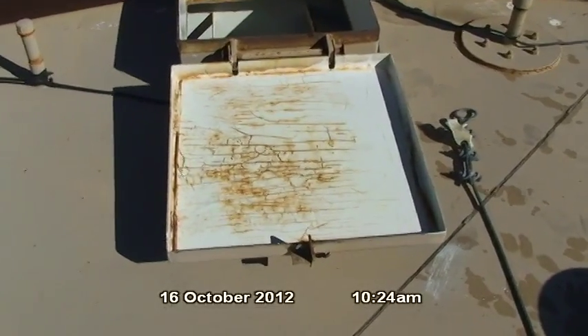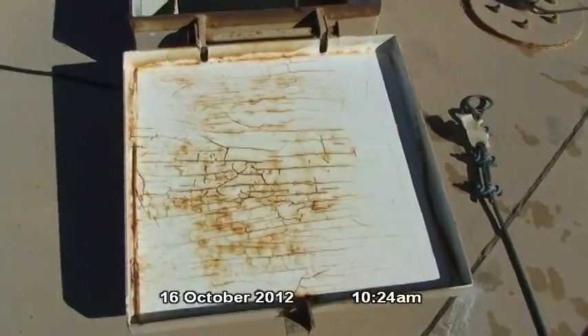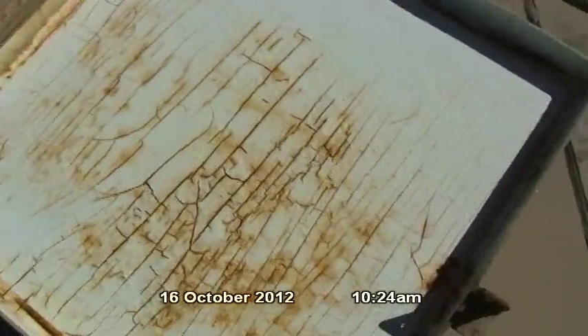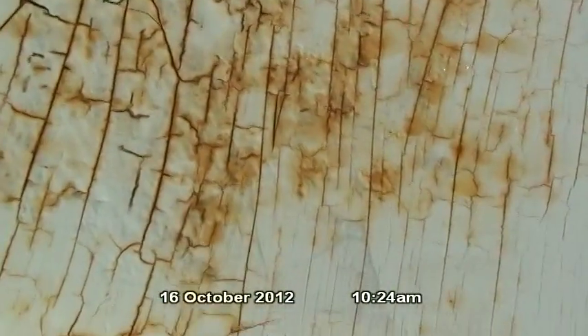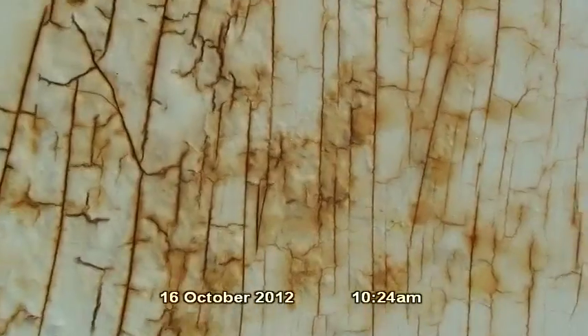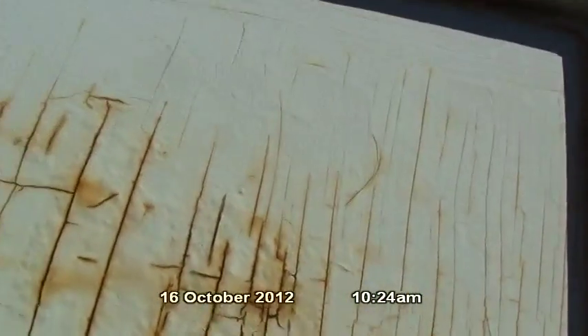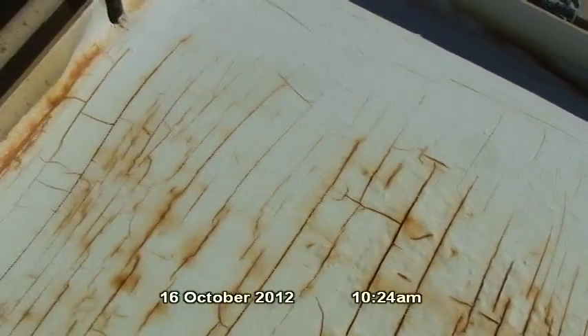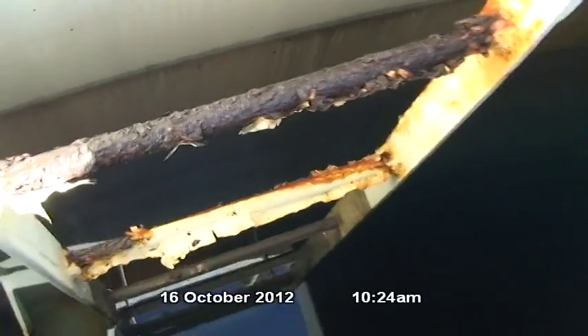The access hatch located on the roof was securely padlocked at the beginning of the inspection. Light surface corrosion is present in many areas on the exterior of the hatch, and the epoxy coating on the interior of the hatch is in poor condition. The coating is losing flexibility and cracking, delaminating in many areas, resulting in light surface corrosion. Here's an example of light surface corrosion on the lip of the access hatch.